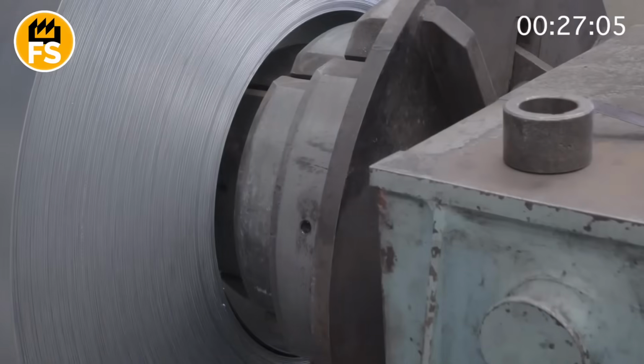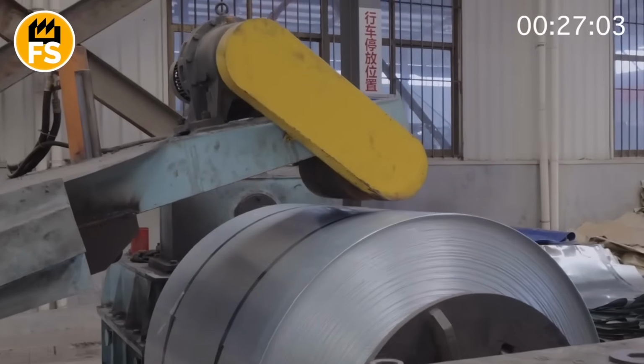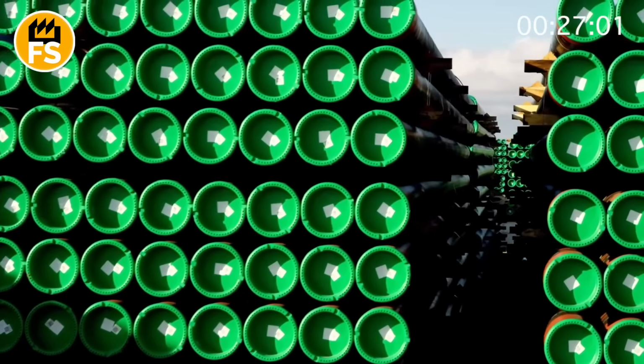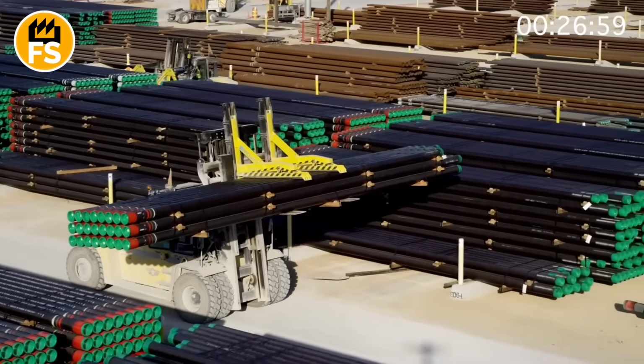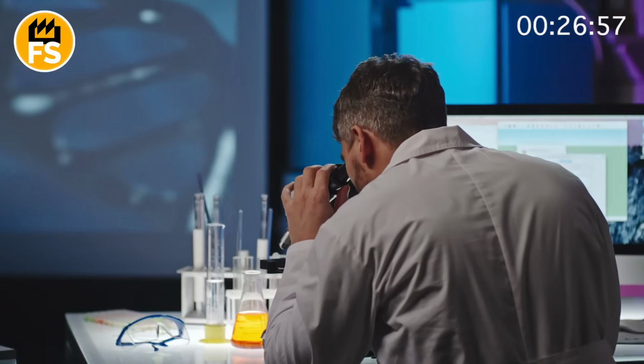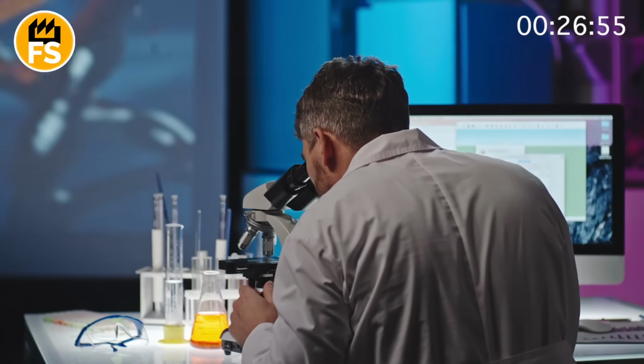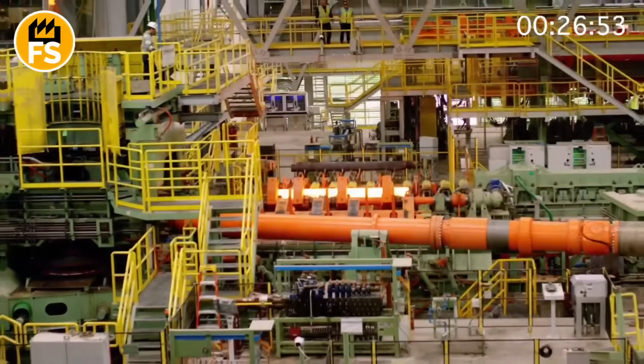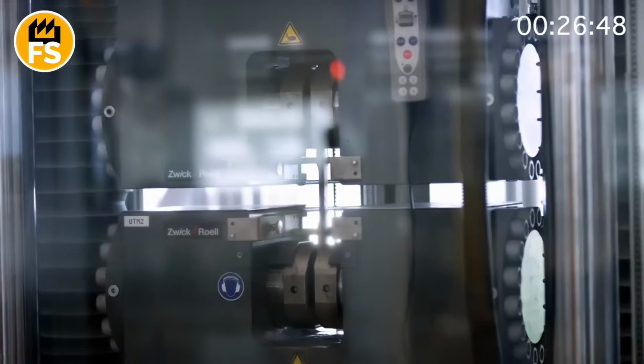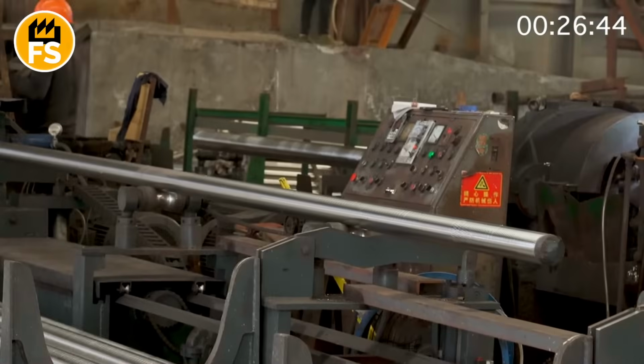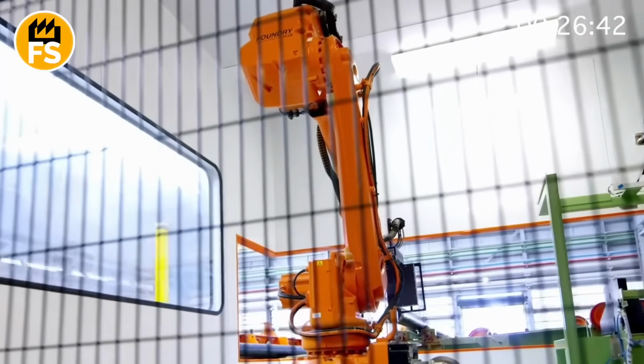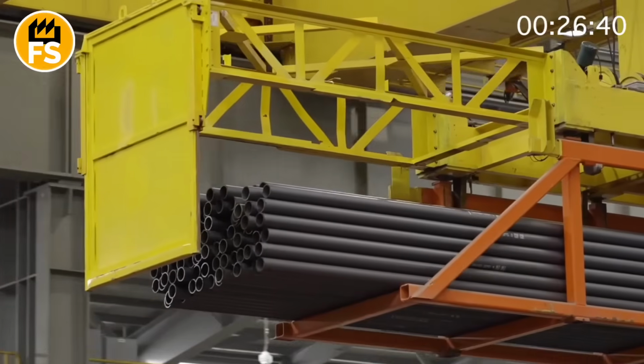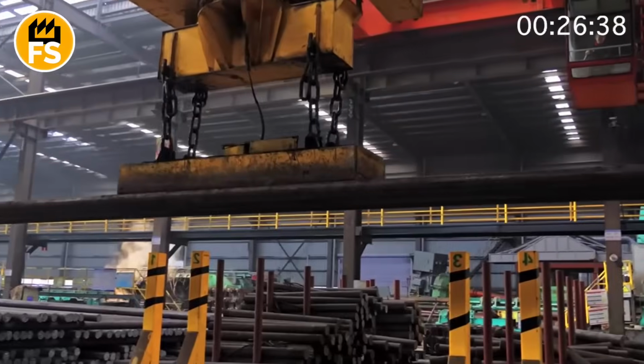Each chemical element glows uniquely, so the device recognizes exactly which elements are present in the steel and in what quantities. How much carbon, manganese, chromium, nickel, or phosphorus. This analysis takes only a few minutes, but provides a complete picture of how well the billet meets technical requirements. If the composition isn't perfect, the batch might be rejected or redirected to other production lines. From 1 to 3% of billets are sent for remelting.